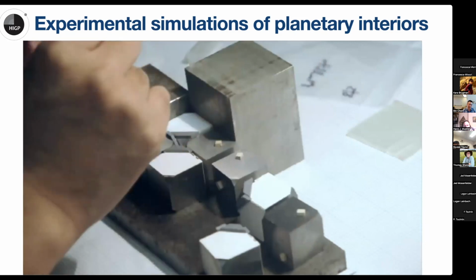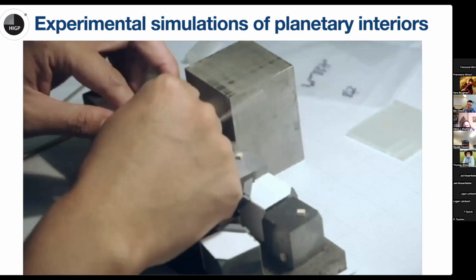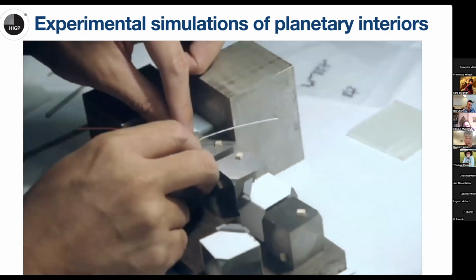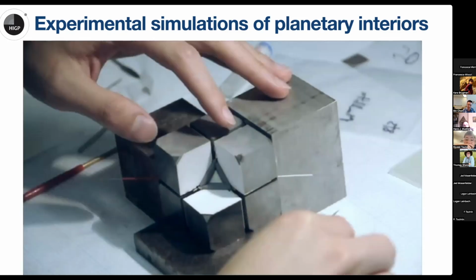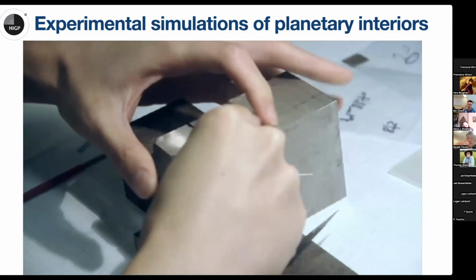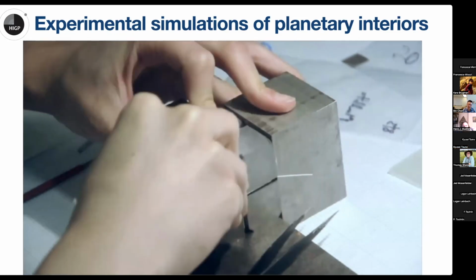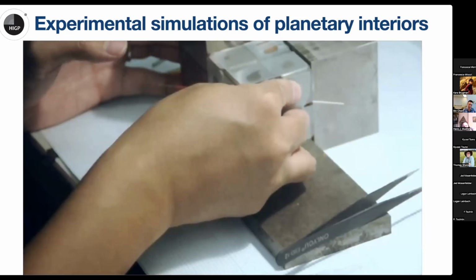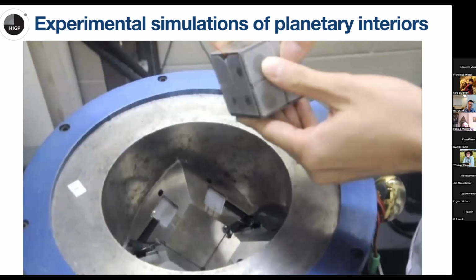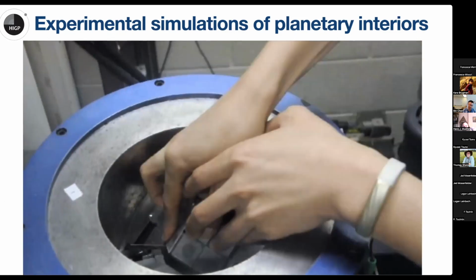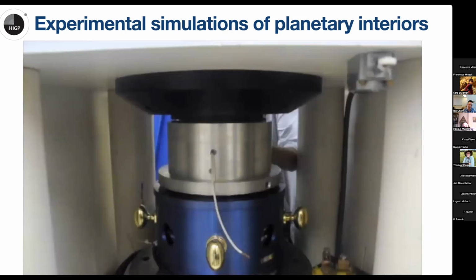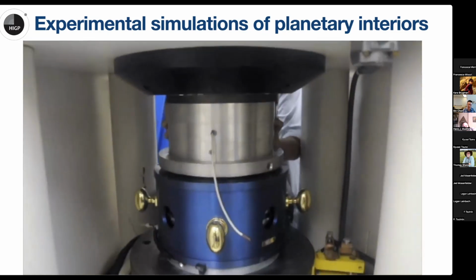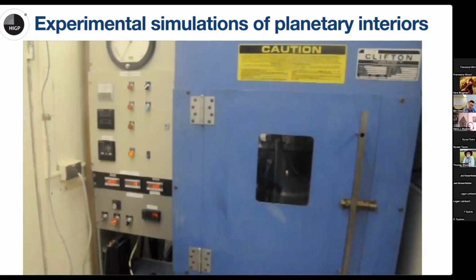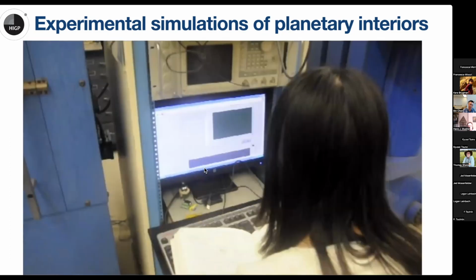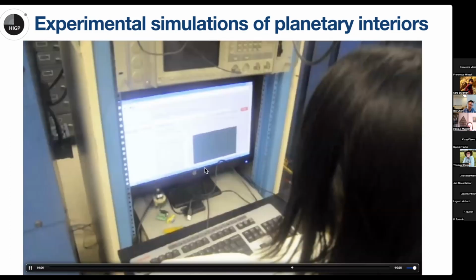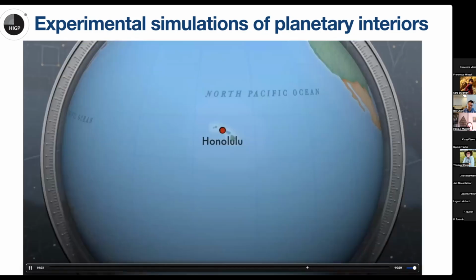The sample is placed inside this octahedron, and then we have a linear furnace for heating and a thermocouple for measuring the temperature. After the cell assembly is assembled, it will form a larger cube, and then it will be placed in our 2,000-ton press. This is a Walker type of module. We compress the cell assembly from the 111 direction of the cube. After we place the spacer, we pump oil to the lower chamber so we can compress our sample. And this is my former student doing the experiment, and we can control the heating using the computer.